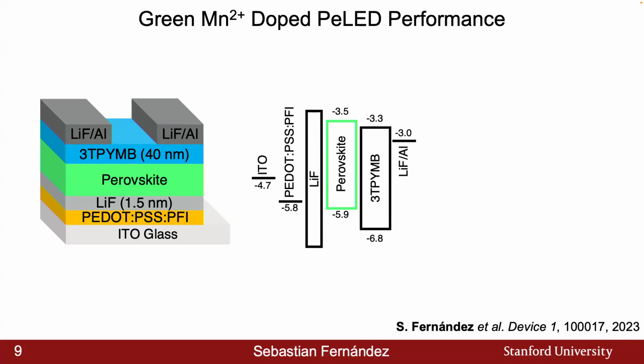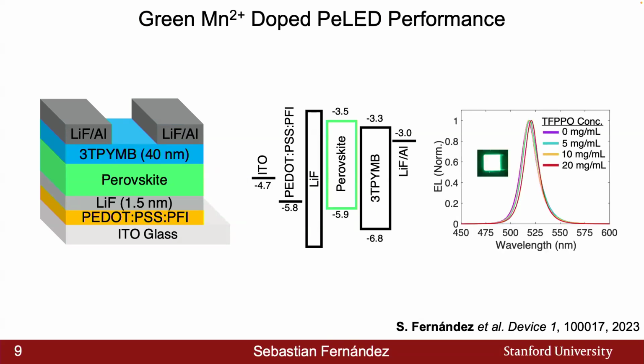Lastly, we also use a more non-traditional electron transport layer, 3TPYMB, because we want to facilitate the electron injection from the lithium fluoride aluminum electrodes, and it's very well aligned with the conduction band minimum of the perovskite active layer. So in general, we can then see across the TFPPO concentrations that we looked at, there is no clear red or blue shift, so no increase or decrease in the wavelength emission from these materials and devices. And it's fairly well centered at 520 nanometers. Within the inset, we can see a very bright green, pure LED.